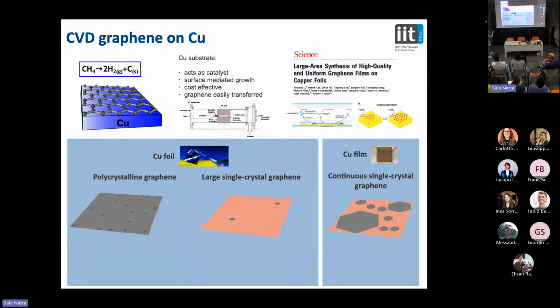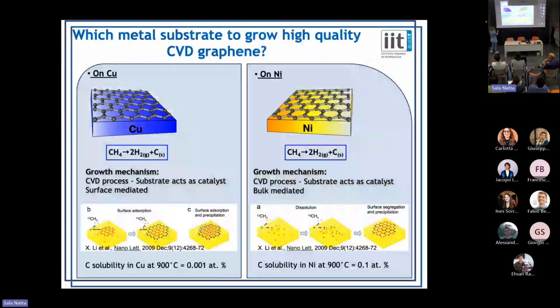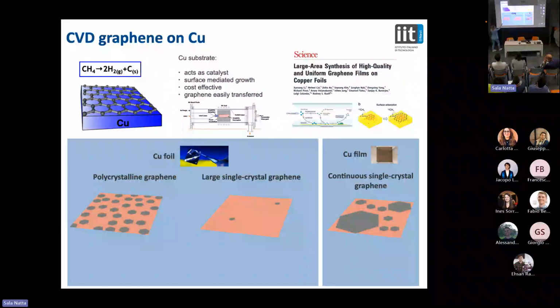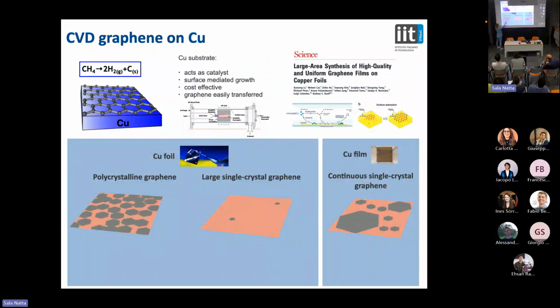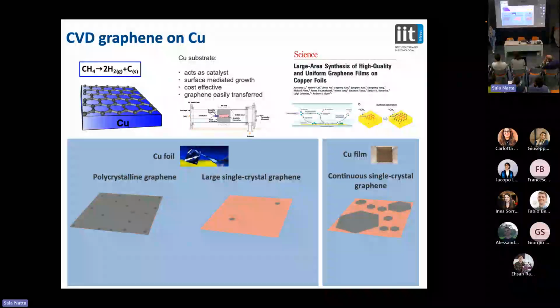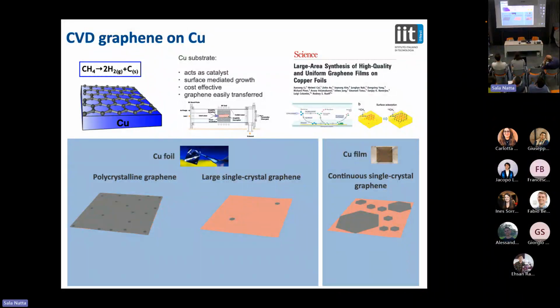And okay, that's when we do a complete growth. So the growth starts like this, continues, and that's a continuous layer of graphene. Here, bilayers joining, but it doesn't get much more than that, even if you completely screw up with the time. So basically, what you will have where these different grains join is that the electrons will actually find defects and will not run so fast.